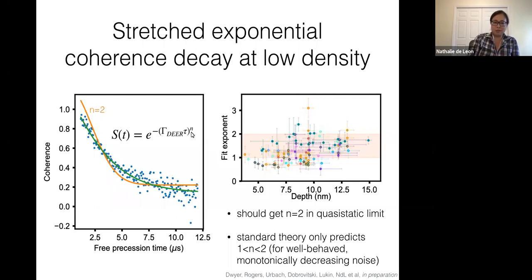And this is very well established and very well known from the spin resonance literature. But what we were seeing consistently was that if you tried to constrain the fits so that this exponent was 2, this was the best fit that you could get, this orange trace here. So it's clearly not the correct shape of this free induction decay. You can see that we have this heavy-tailed distribution, some kind of stretched exponential decay.